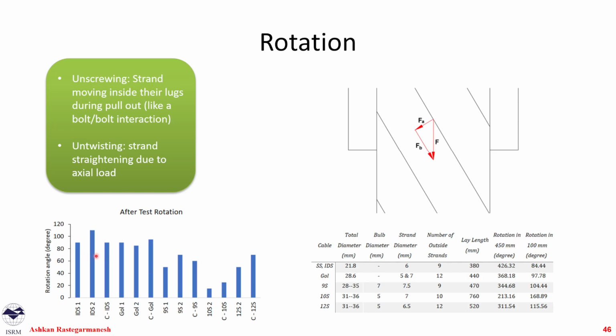And then after each test, we realized that regardless if our tests have rotation constraint or not, our samples will rotate. They either rotate during the test, or we constrain the rotation, and at the end of the test, when we release the load, our samples will start to rotate and go back to a certain angle. And this value is the rotation angle that we measured after the test.